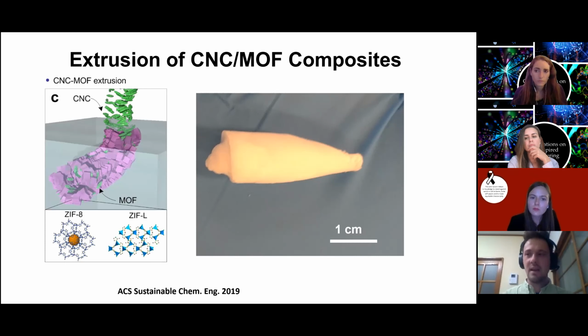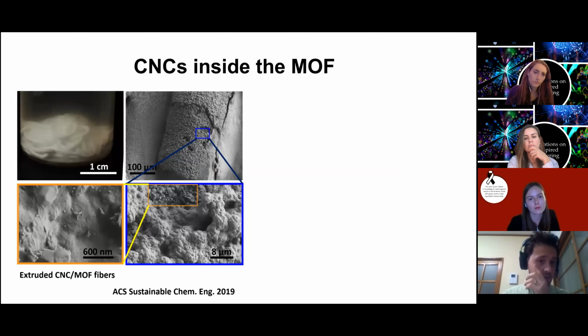And like I said, they often are very hard to form these MOFs without some seeding molecule, without a sink. And so no crystals form if you just have those two ingredients. But once you put in those cellulose nanocrystals, immediately you get crystallization along that interface, which allows you to make these beautiful hydrogels. This is some pictures of those fibers.